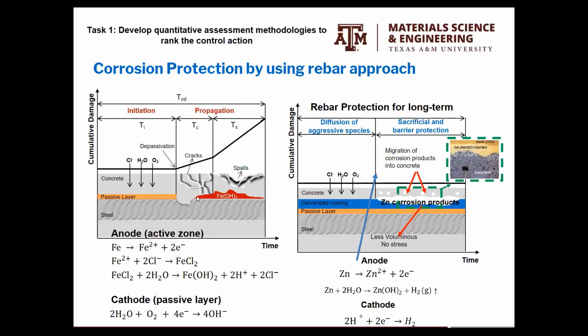And that active state will also form corrosion products. In that propagation state, you see the accumulation of damage can go in this direction, can go even with a higher slope, but that's the schematic. So what we are doing in this project or in this approach is putting an additional, let's say, protective layer, not only the passive layer that you have originally in the steel, but we are putting a galvanized layer. And we know that this is not a new technology, but it's a technology that we think is worth exploring in detail.